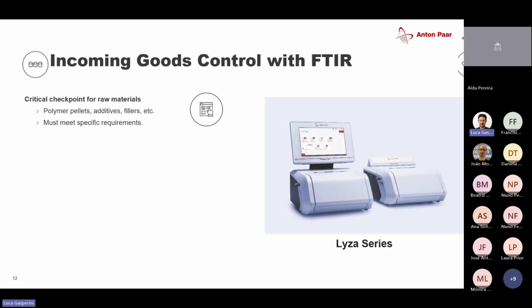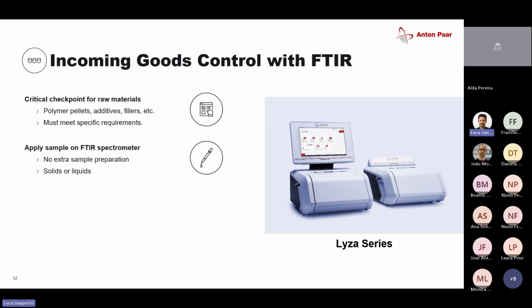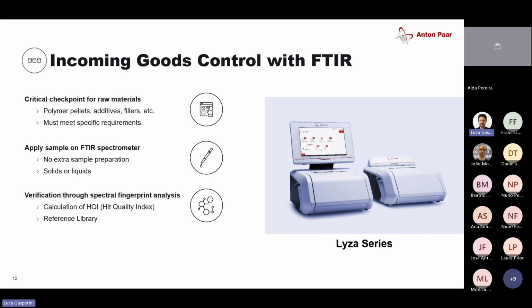So there we go. We start with raw materials. As I said, a simple verification. So I receive raw materials, can be polymers, additives, fillers, whatsoever. And I want to know if the quality of the supply is actually what I expect from it. So I can do a simple verification test without any sample preparation with an ATR crystal, for example, and get a very, very fast response. Within 30 seconds, I know if the sample I received is actually the sample I would expect.